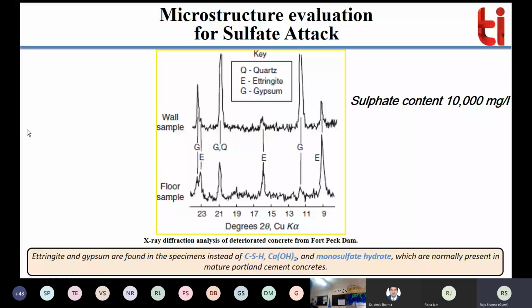This is the X-ray diffraction analysis of deteriorated concrete from Fort Peck Dam, in the US. They found that some area of the wall and some area of the floor is degraded. The concrete is degraded from the top surface, and the particles get eroded from there. Other structure is very good, but some of the patches are severely affected by the sulfate attack, and because of that, degradation happens and keeps on increasing.